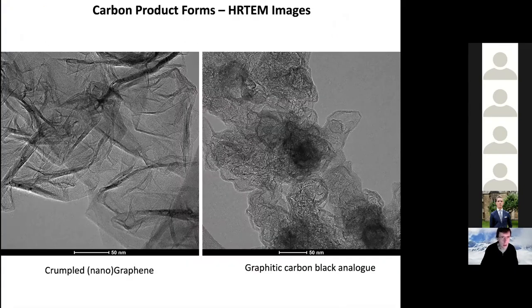of graphene versus more exclusive production of this graphitic carbon black-like material that is seemingly heat treated, shall we say. So again, just highlighting and contrasting the 2 products produced in the aerosol phase, and that's why you might hear the term freestanding, produced directly as an aerosol. That is also quite surprising when you think of combustion and other types of pyrolysis processes, that you do not necessarily form nanographene as a freestanding aerosol by direct particle nucleation, speaking to why the plasma is somewhat different in that regard. Versus again, the graphitic carbon black analog, just again showing the outline of the graphitic lamella on the particles themselves. Again, these are highly overlapped, merged, somewhat fused in a compact fractal aggregate.